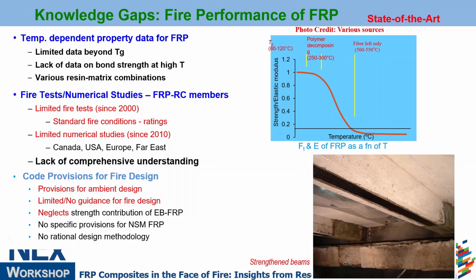It used to be about 60 degrees when we started this work about 15, 20 years ago. Now they have moved on to 80 to 100 degrees or maybe sometimes 110 degrees in the current FRPs. So once it reaches Tg, then what happens? The polymer starts decomposing. And at 200 or so, much more decomposition happens, completely gone. Around 500 degrees, this graph has moved based on fitting all these logos here, so don't pay too much attention. I have some test data I'll show you. But anyways, this is the trend at which the material properties, tensile strength, for example, degrade.